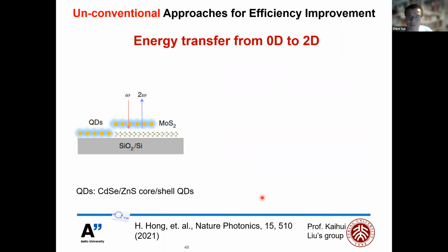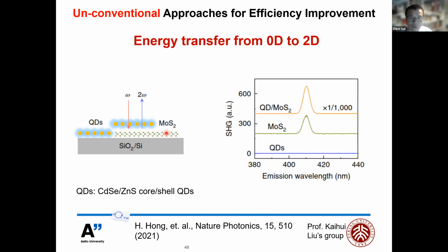Just recently, we also demonstrated a new way to increase the nonlinear response by energy transfer. These are the devices fabricated by Kaihui's group in China. They coated a thin layer of quantum dots on the monolayer MoS2. Because the quantum dots have a centrosymmetric structure, we don't observe second harmonic generation from them. However, when we put the quantum dots on the MoS2, we found that the second harmonic generation has been enhanced by more than 1,000 times. So this is really amazing.